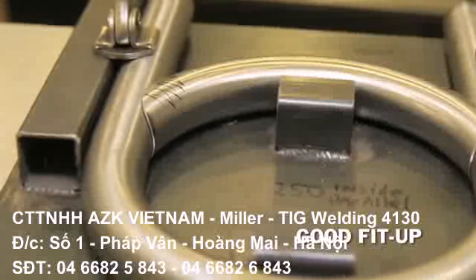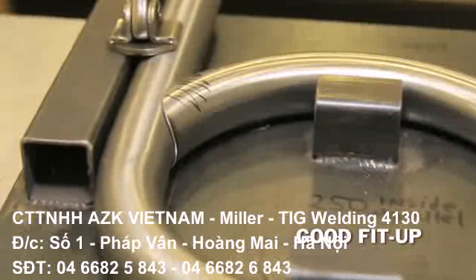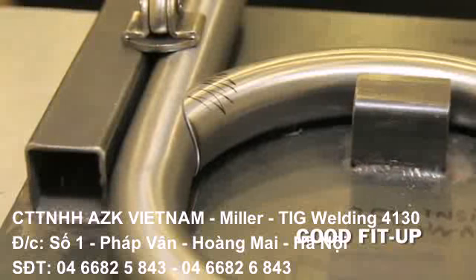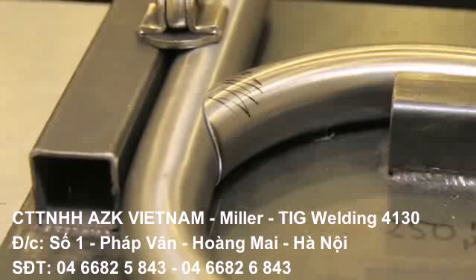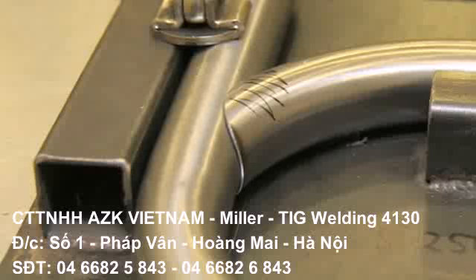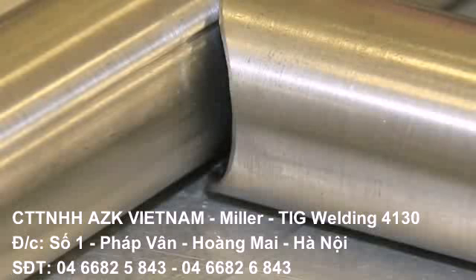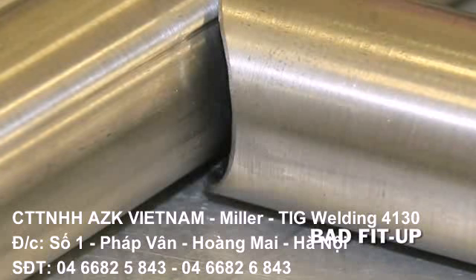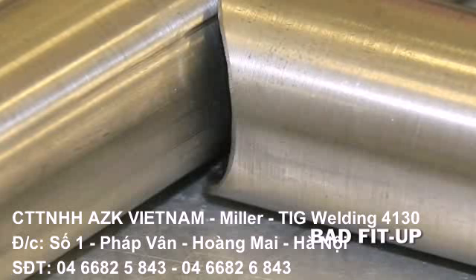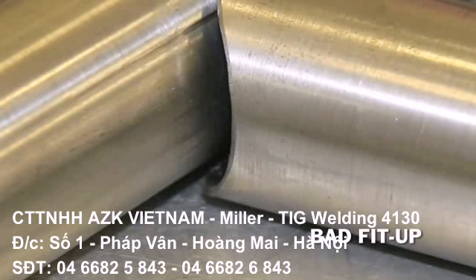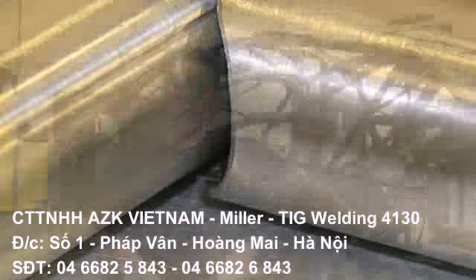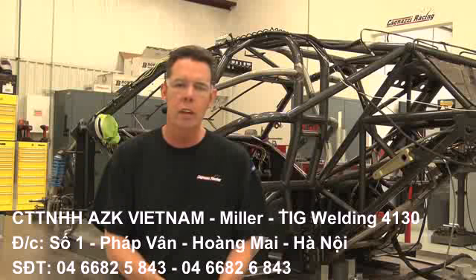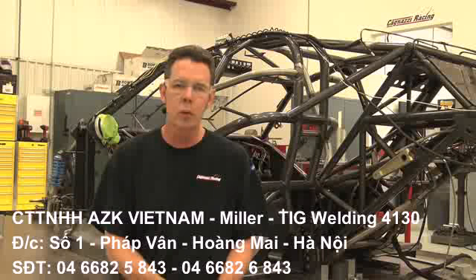If I have a fit that's not very good and I'm having to use a lot of filler rod and a lot of heat to get it to bridge the gap, then I'm risking the possibility of embrittlement around the weld area because of the heat concentration. So we try to make the fit as tight as we can without creating any gaps, so we can use a little less filler rod and accomplish the same goal.